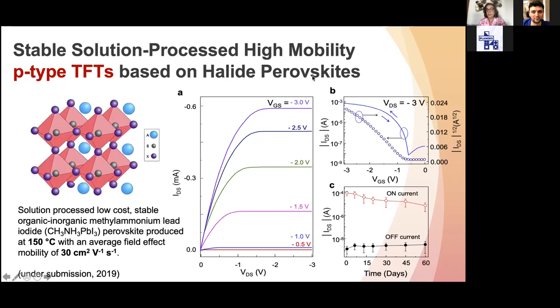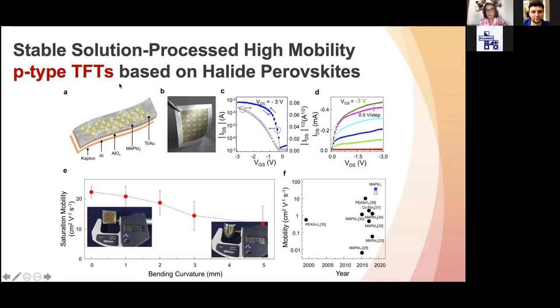As you know, in the area of metal oxides, they are basically N-type. And if you are looking, for example, for CMOS applications, we need to have both P-type and N-type semiconductors. And these halide perovskites work quite well as P-type TFTs. And here we have some examples. At that time, this was not yet published, but it is already published in ACS Nano. And we are also able to make these TFTs on polymeric substrates, even using a very low process temperature.